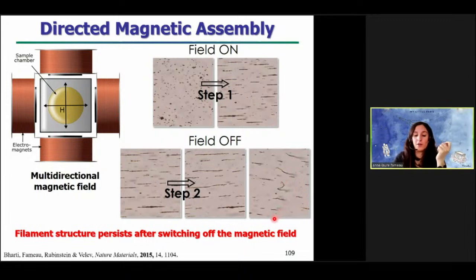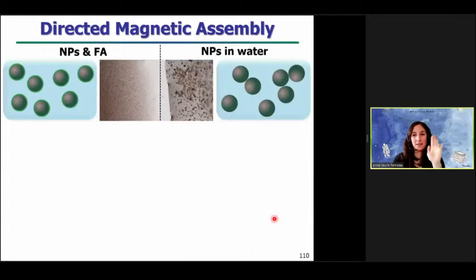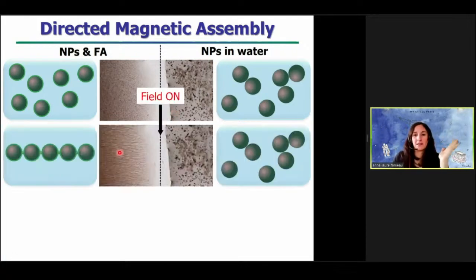So to understand how the filament structure persists after switching off the magnetic field, we did a simple experiment first. We took a microscope glass slide. We put a hydrophobic spacer in the middle, as you can see here. And on one side, we put nanoparticles capped with fatty acid, and on the other side, we just put nanoparticles in water. We apply the magnetic field in this direction, like this. We observe the formation of filaments for fatty acid capped nanoparticles, and nothing happened for nanoparticles in water.